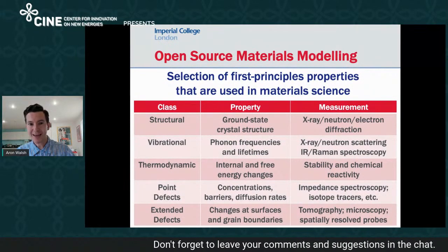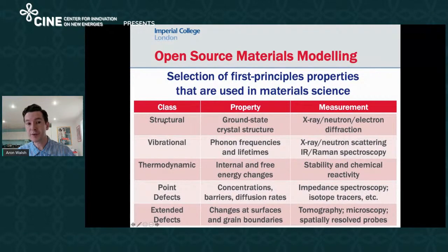And I would say there are several classes of things that we can calculate. So it can be structure; we can do structure prediction. We can think about vibrations and compare to infrared and Raman. And we can think about thermodynamics, compared to calorimetry measurements, for example. And increasingly point and extended defects. So we can predict what defects should be present, how they might diffuse in a material, and compare, for example, to impedance spectroscopy, to tomography, and to a range of different microscopic probes in crystals. And we're seeing many examples in the literature of how well modeling and measurement can match when comparable experiments are performed.